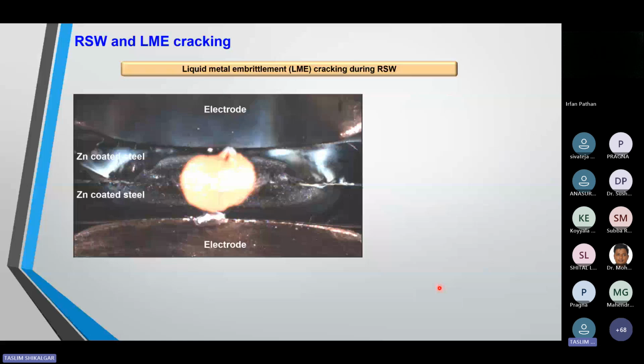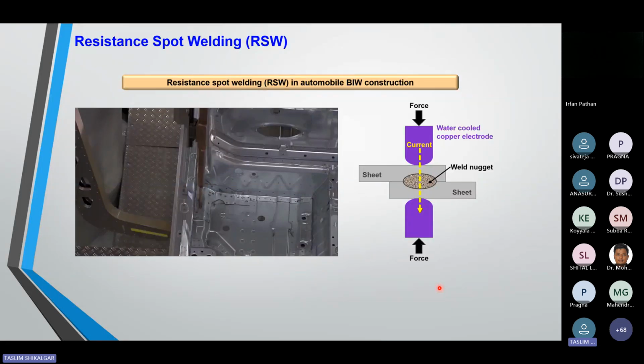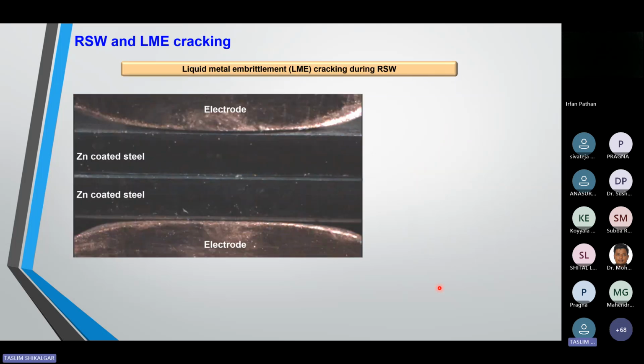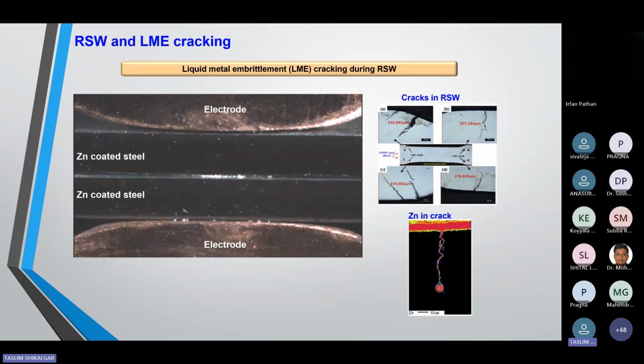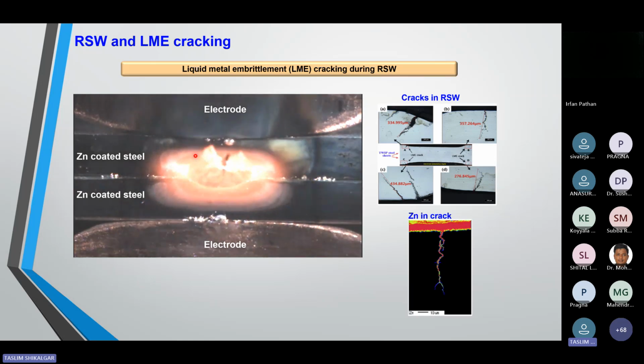In this previous video, you can see so many joints are available and all joints are made by this RSW. And every joint is having cracks. So you can see how many cracks are available in the BIW. That is the important challenge. Not a single crack, so many cracks. So people are still working on this. So here is one of the challenges. They can make this RSW nugget, and from this nugget they can generate one small specimen, and with the help of the specimen they can find out the fracture properties as well as the mechanical properties.